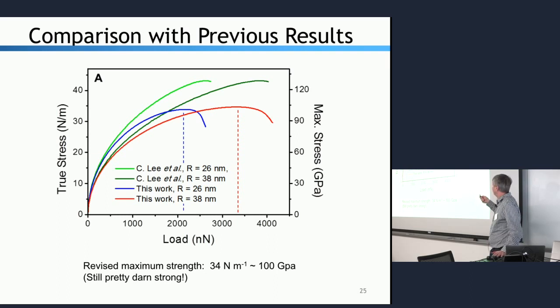And now when we plug in, say for the 38 nanometer tip, if we break at about 3,400 nanonewtons, we can see that that corresponds to a breaking strength of about 35 newtons per meter. So this is actually a little bit weaker than we thought before. So it's about 34 newtons per meter. This is about, this should be capitalized, about 100 gigapascals. So in the original paper we said 130.